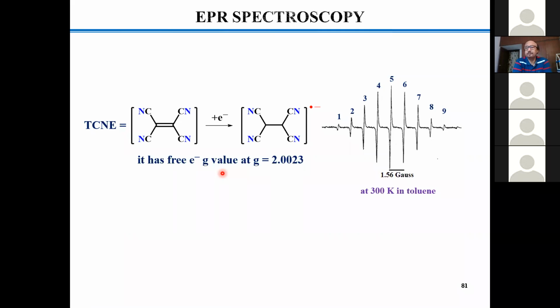One is called the TCNE radical, tetracyanoethylene. This is not a radical by itself. You have to reduce it, and then you will get one electron, that is one radical, and its g value is fixed at 2.0023. This radical is a very nice radical, but you have to put it in a sealed tube, because on exposure to a minimum amount of oxygen, it goes back to the initial neutral, non-radical state. And TCNE shows a beautiful 9-line spectrum, which is natural. There is one, and then 4 equivalent nitrogen-14, so it gives you a 9-line spectrum. But if you use a small pinch, say 1 micro something, then you won't get the 9-line splitting, you will get a single line.